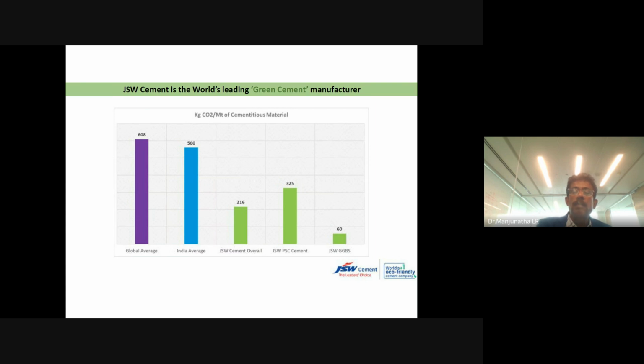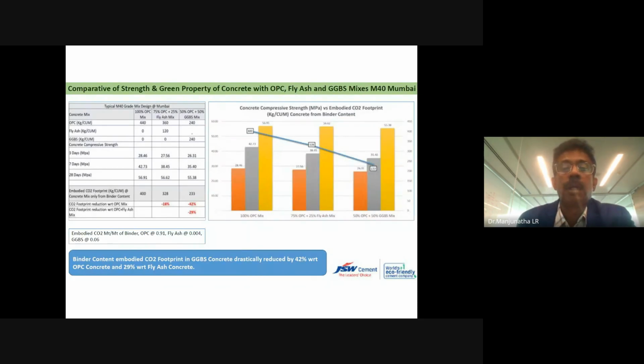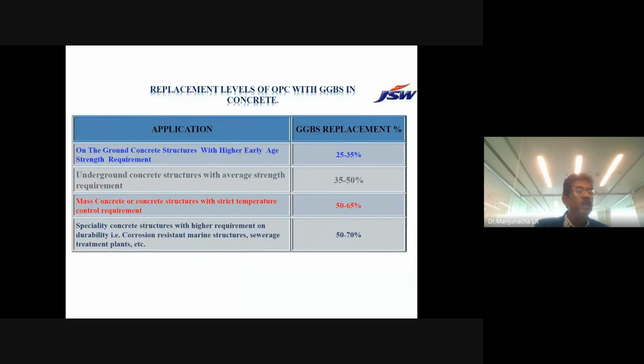The world leading cement manufacturing company, JSW, has become the lowest carbon footprint company in the world compared to any other company in India or abroad. This is the next best example, and I've just done a calculation of how much emissions are coming down. We have a 100% OPC mix, 25% fly ash with 75% OPC, and 50% OPC with 50% GGBS mix. In this M40 grade concrete, with the fly ash mix the CO2 emissions have reduced by 18%, whereas with the GGBS mix, emissions have been reduced by 42%. That is a beauty. The difference between the fly ash blended and GGBS blended is almost 29%. Similarly, for various applications like ground slab with early strength, we can use up to 35%.